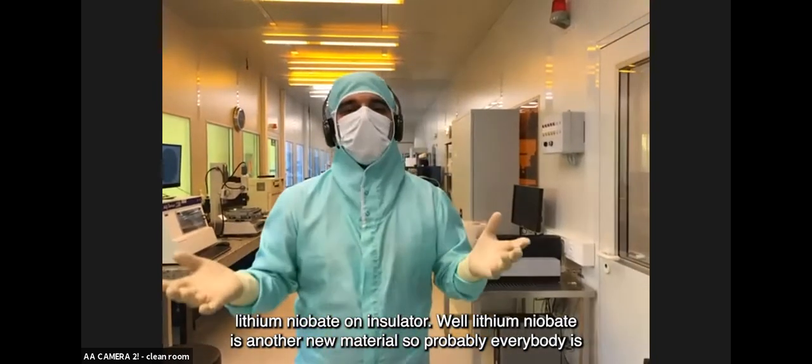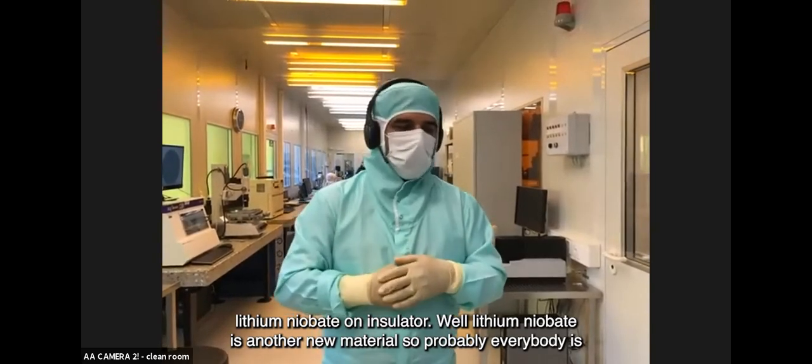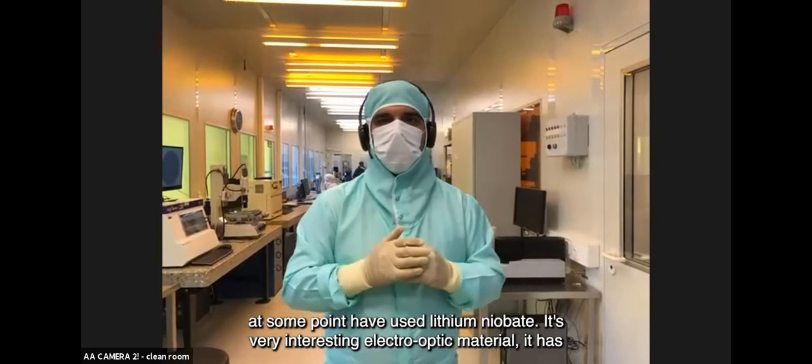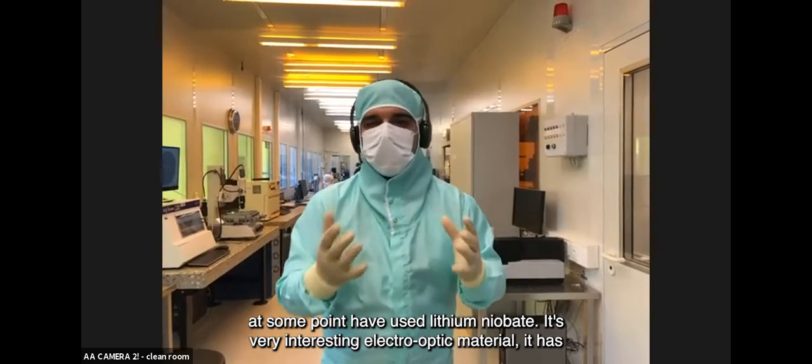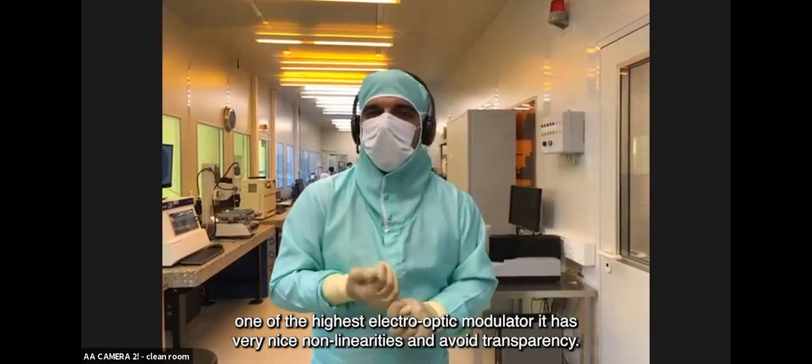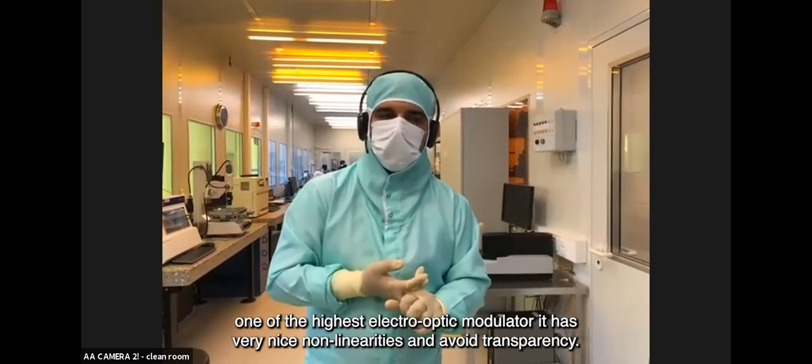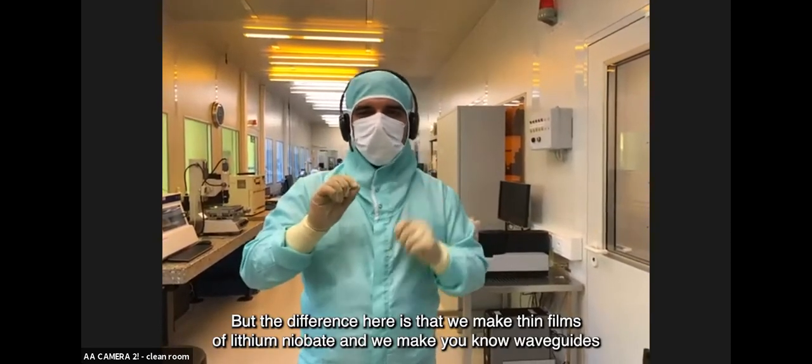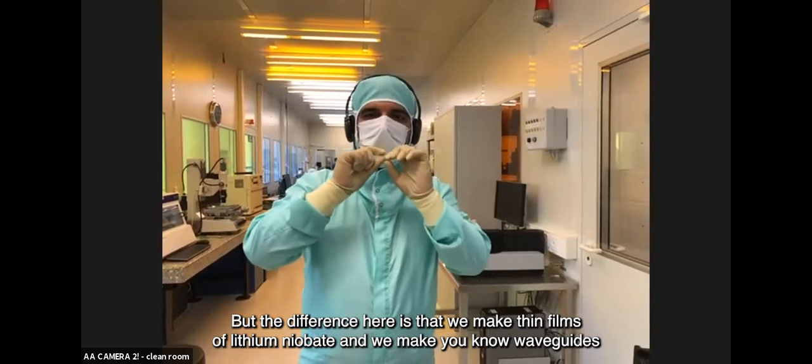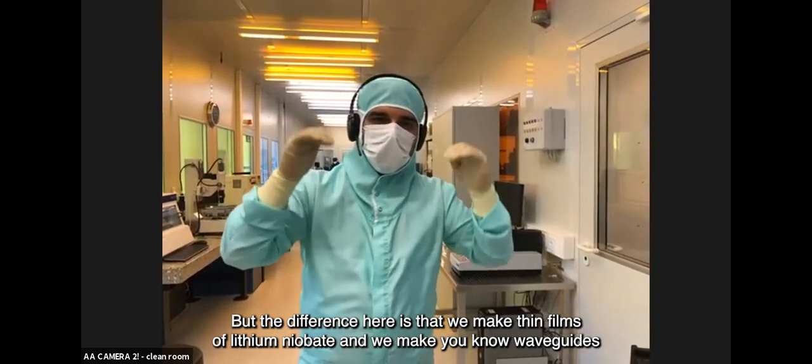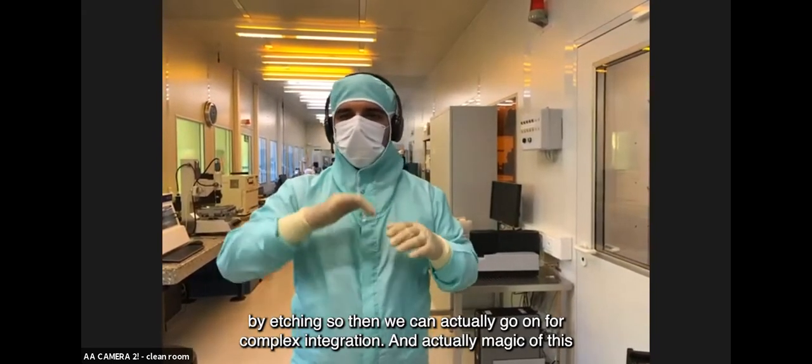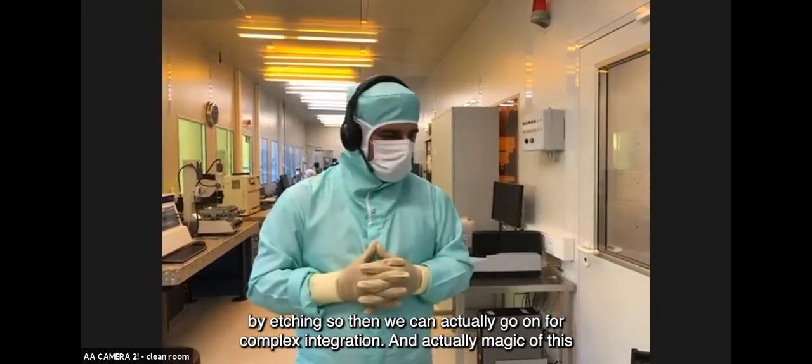Lithium niobate is not a new material - probably everyone has at some point used lithium niobate. It's a very interesting electro-optic material with one of the highest electro-optic modulators, very nice nonlinearities, and a wide transparency window. The difference here is that we make thin films of lithium niobate and make waveguides by etching, so we can actually go on for complex integration.